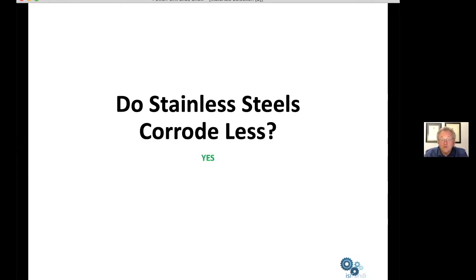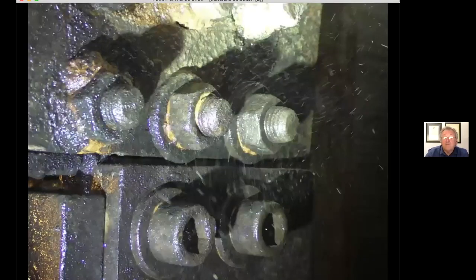Well, the short answer is yes. But the caveat to that is that they only corrode less if they are correctly utilized and their limitations are kept in mind. And when you do that, then you land up with a very successful corrosion-resistant situation. And this photograph is of a submerged component in a highly corrosive water system, which has been in service in excess of 20 years and is still as good as new.